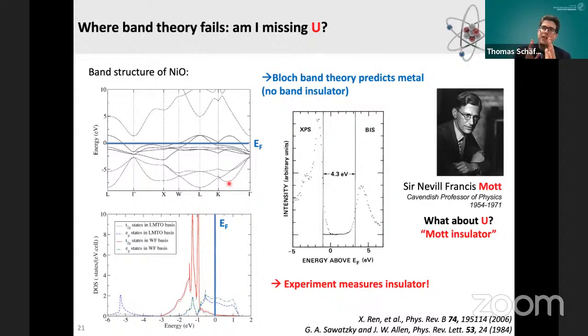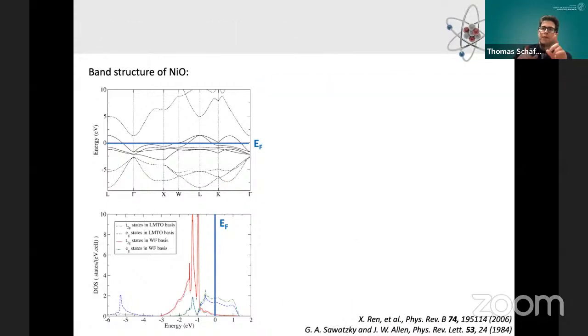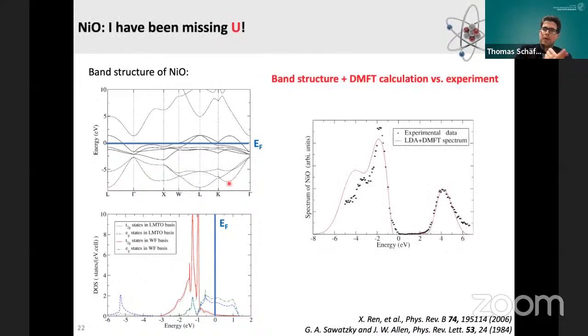We can do a combination between band structure calculations, so for example DFT, density functional theory, and DMFT, which is called LDA plus DMFT. So we have included the crystal structure, the band structure, plus the Hubbard interaction. And you see now that if we compare this LDA plus DMFT spectrum, which includes the correlations, with the experimental data, we almost lie on top. So in this case, what is really making the difference is the correlation physics, so the Hubbard U.